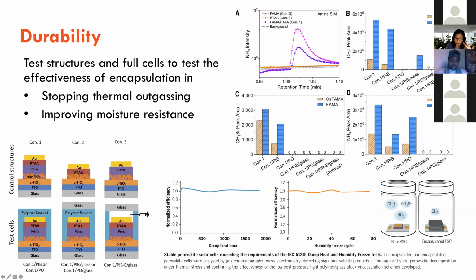What we found is, people think encapsulation is to protect the cell from external elements so that moisture can't go in. But in fact, it's protecting the cells from moisture as well as stopping the thermal decomposition. If you have this blanket approach, the gas can't come out. It's got no way to come out. Whereas if you use the edge sealant, it can come out to the void and therefore drives decomposition reactions. So that's one of the major findings that is not known in the community, and we managed to confirm the bifunctional, the two functions played by the encapsulation: to stop things from going in and to stop the decomposition reactions from happening, because it's airtight encapsulation.